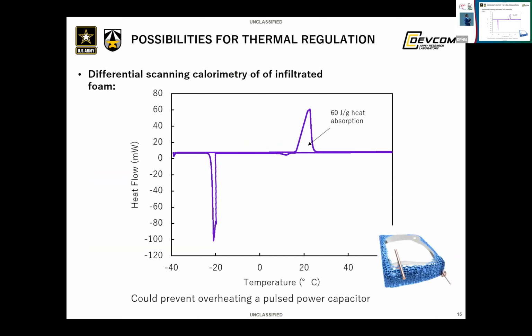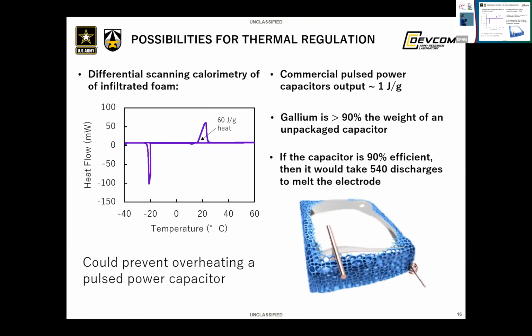Now, one of the more creative possibilities for this is the opportunity for thermal regulation. So this is gallium, and gallium melts at 30 C, and it supercools a whole bunch. So you could melt the gallium, and then you'd have plenty of time to try to infiltrate it into the foam, and then it would solidify. And so this DSC measurement, you can see, has 60 joules per gram of heat absorption that takes place right around this transition. This was probably not pure gallium, it was an alloy, because I'm seeing them way off.